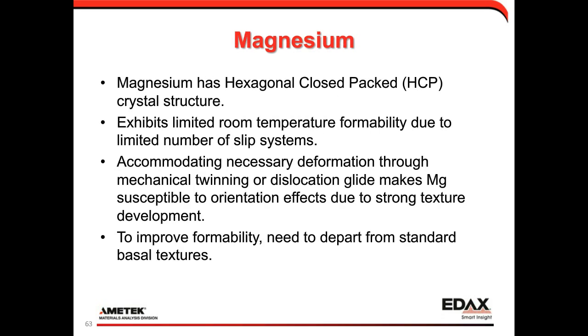And again, that applies to magnesium because it's hexagonal close-packed, with a limited number of slip systems available at room temperature. Accommodating the deformation through twinning or dislocation makes magnesium susceptible to orientation effects, and therefore susceptible to texture effects. So to improve formability, we want to get away from these basal textures we showed from that example.